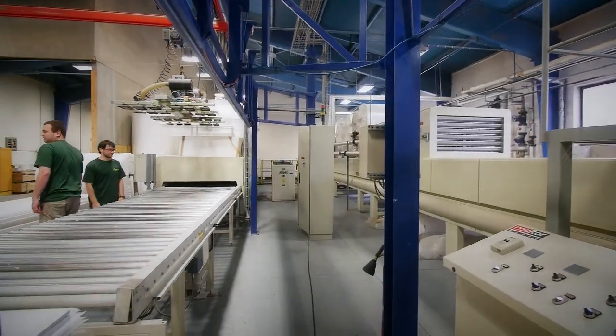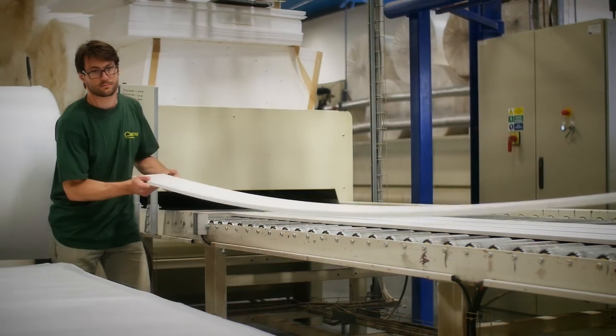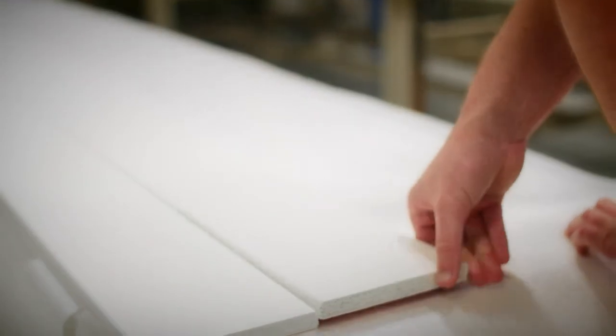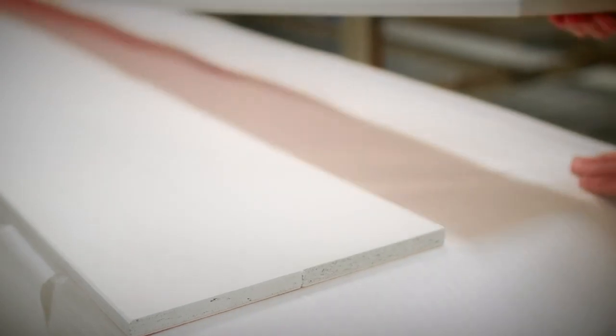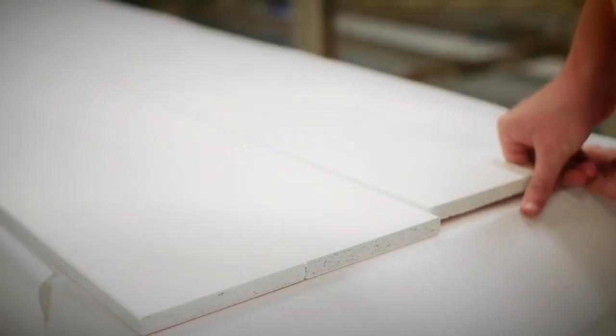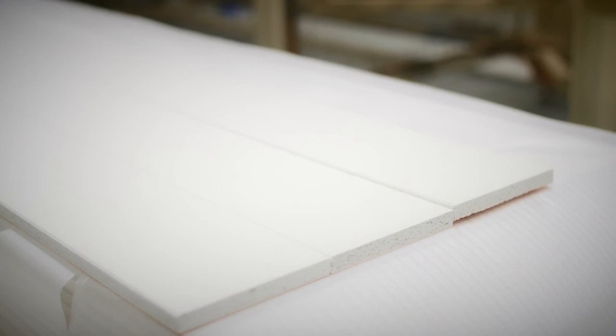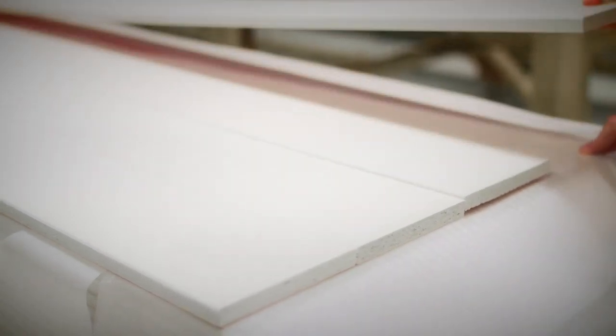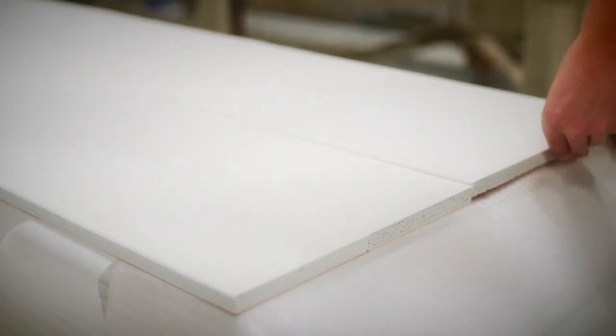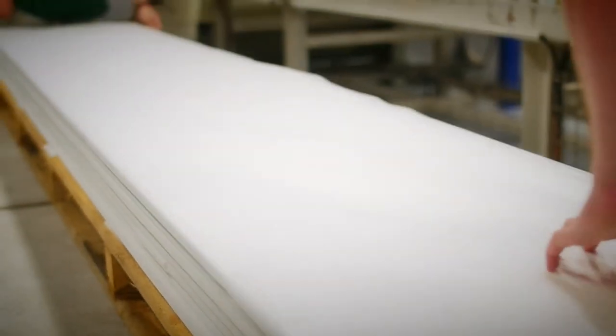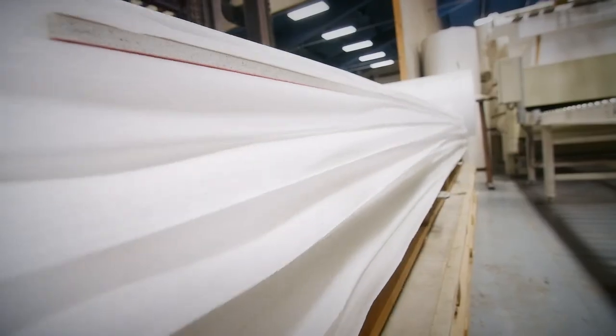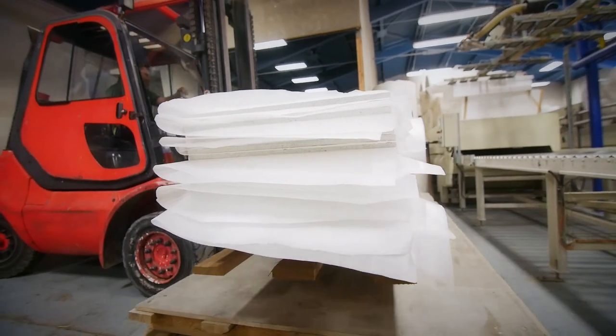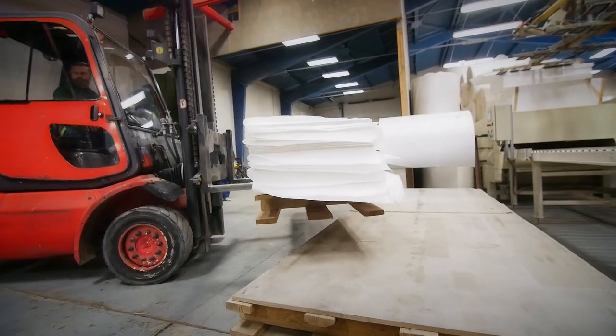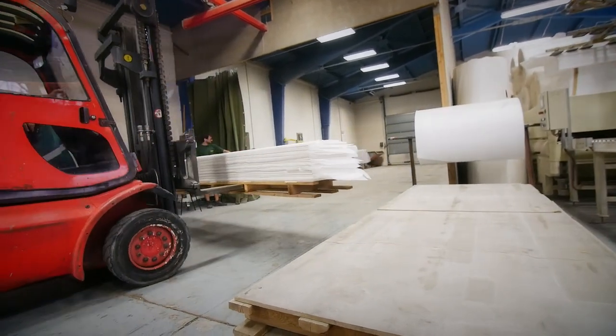The temperature of the panels with the surface treatment is decreased in the cooling zone. In a 12-meter-long tunnel, the boards are cooled down by flowing air so that the temperature of the boards at the output does not exceed 25 degrees Celsius. At the end of the line, the facade boards are stored on wooden transport pads, either using a manipulator or manually. Each facade panel is underlaid with a plasticized foil for protection of surface treatment against dirt and dust. The ends of the boards are covered with a protective permeable foil and tied together.